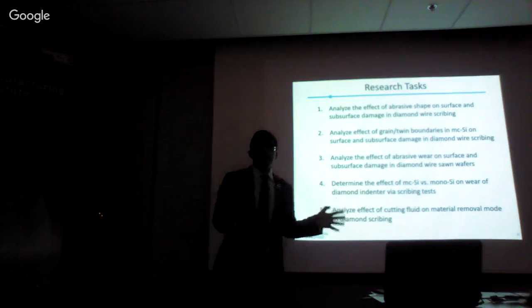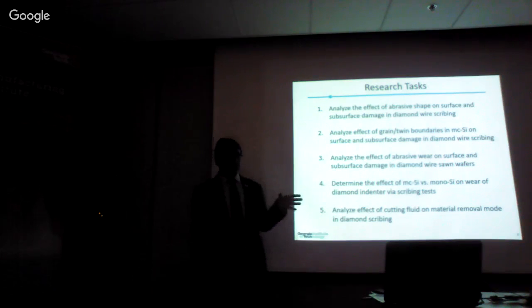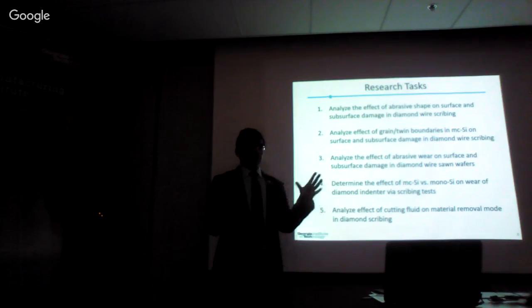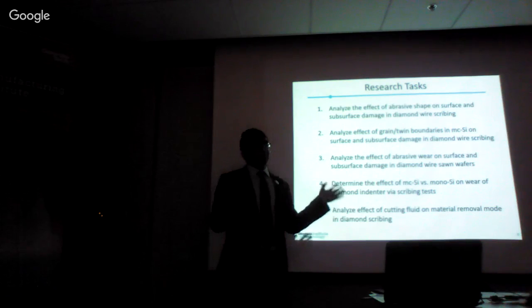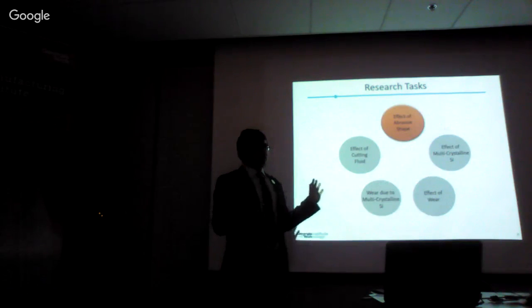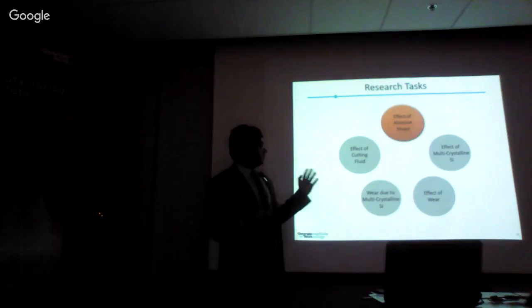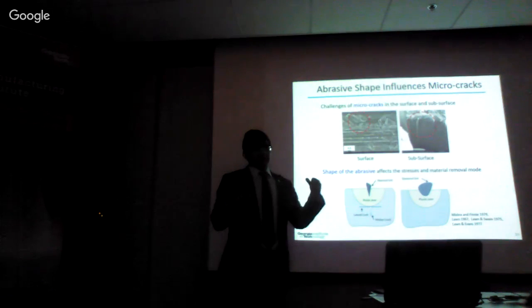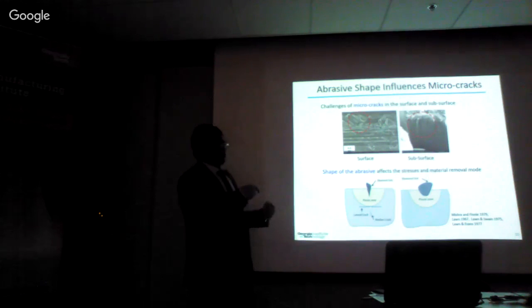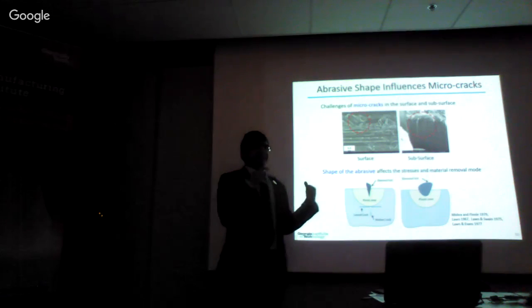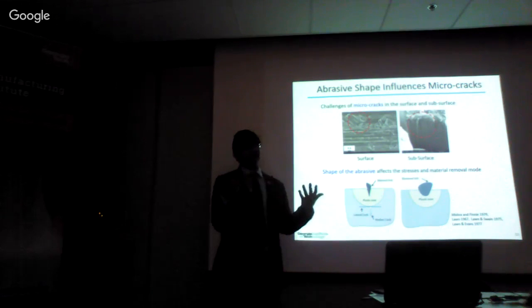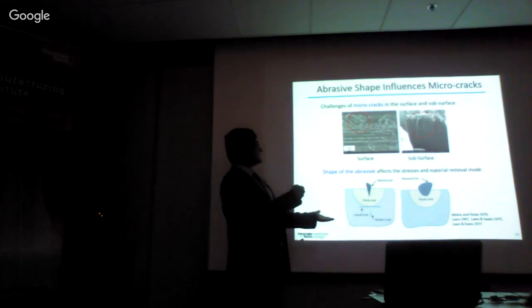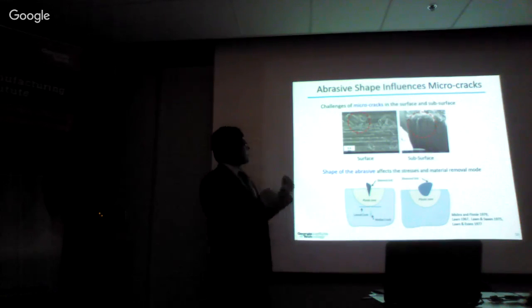And finally, to analyze the effect of the cutting fluid on the material removal mode in diamond wire scribing. Moving on to the first task, which is the effect of abrasive. As we revisit, the major challenge in diamond wire sawn silicon wafers is the mechanical strength, the fracture strength, affected by the micro cracks on the surface, as seen here, as well as the subsurface.